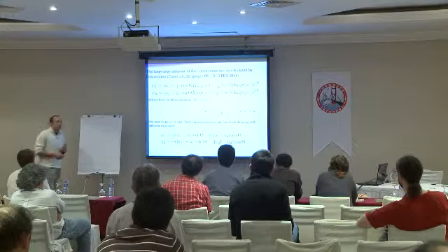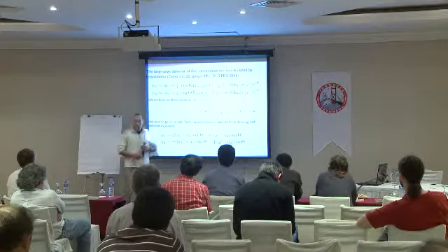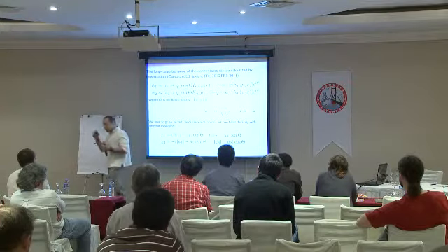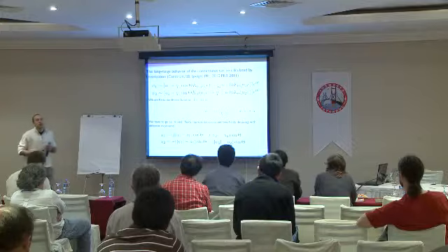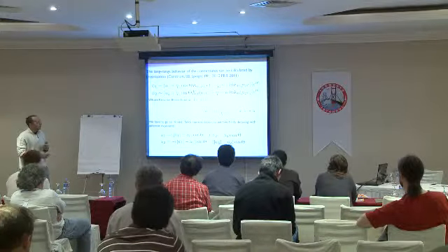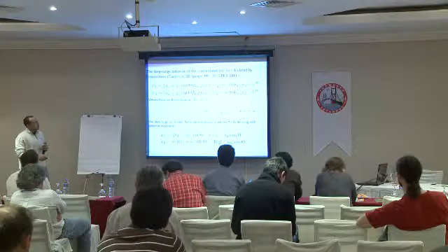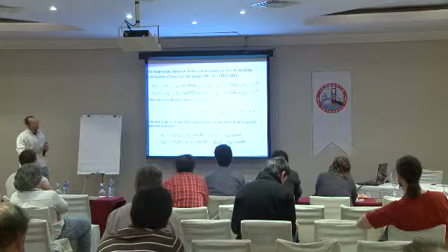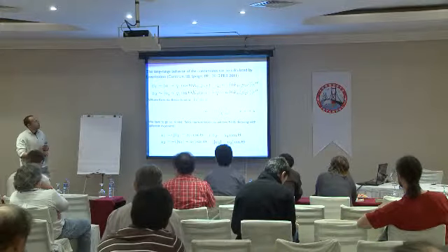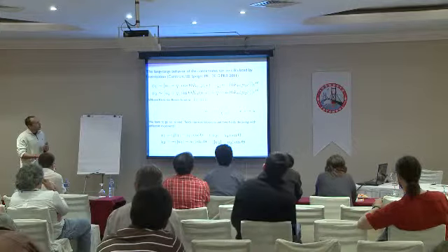That's one thing. But the other thing is that both fields will have contributions in the asymptotics with two different characteristic exponents. So you can represent them as two basis functions, with inverse coherence length 1 and inverse coherence length 2. We haven't defined what they are yet, just so far defined them shortly.